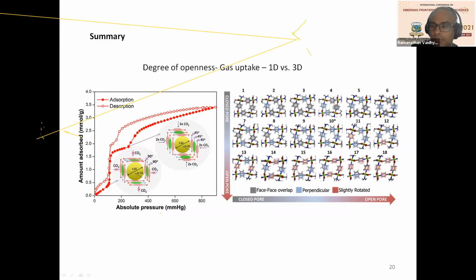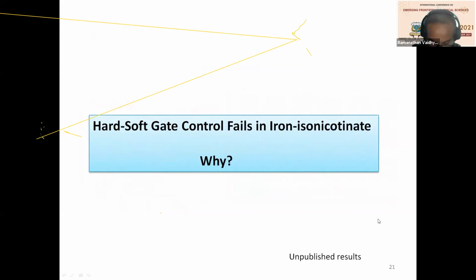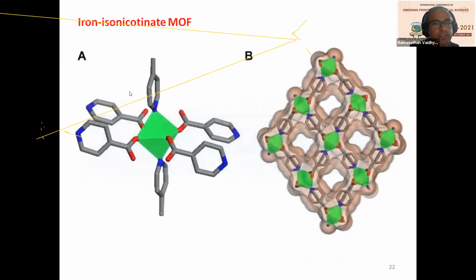openness. This has all been done through extensive molecular dynamics calculations, where we freeze the framework and the sorbate is allowed to move freely. Several snapshots of the molecular dynamics configurations are taken for statistical analysis. Then you identify each data point as a statistically analyzed point, and you get an equilibrium isotherm from which this is claimed. I think I have another 5 minutes, so I'll quickly conclude.